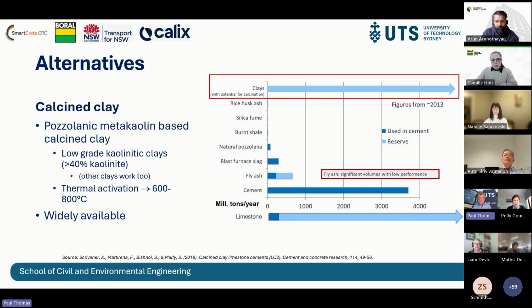We do have to put some energy in - we need to calcine it, dehydroxylate it, activate it in order to make it a pozzolan. However, the temperatures are relatively low - I've got 600 to 800 here, Camille had 650 to 850, so it's somewhere in between there that you need to calcine it. But these are the sort of temperatures you can achieve using electric furnaces - in our case, a flash calciner. If you're using electric furnaces, you can use renewable energies, and that brings the embodied carbon down to very close to zero. Then it becomes a transport issue rather than a fossil fuels issue.